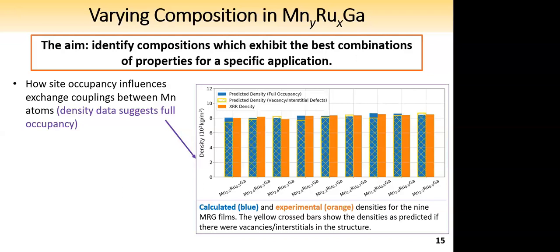Then using nominal compositions of densities, I calculated it for full occupancy, which is given by the blue bars, and also allowing for vacancies or interstitials. And those are given by these crossed yellow bars on top of the blue bars. So then when we compare the two sets of data, we see that we have an indication that in all the film compositions, we have full occupancy of the sites. And this suggests that there will be chemical disorder which can influence the exchange constant. So this is something to keep in mind, and I will discuss this in this part.